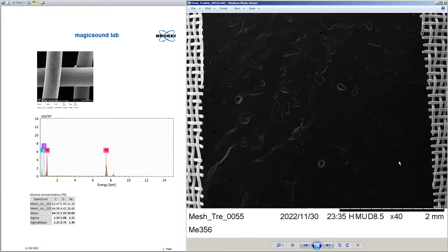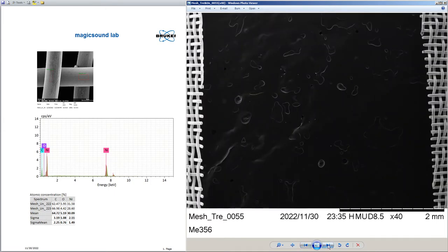This is again the secondary electron image, and it gives us this nice three-dimensional spatial ability to see structure, and that's the advantage of the secondary electron gun. Now the backscatter image is here, and you see a little less of the form than you do on the secondary image, and you lose the carbon tape form here, but you can see that this is darker, and when you're using a BS image, a backscatter image, that's giving you an indication of the elements. And so what you are essentially seeing is that in this case, this is a lighter element and this is a heavier element. So this was very encouraging to see.